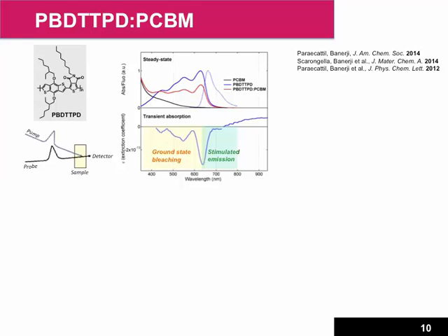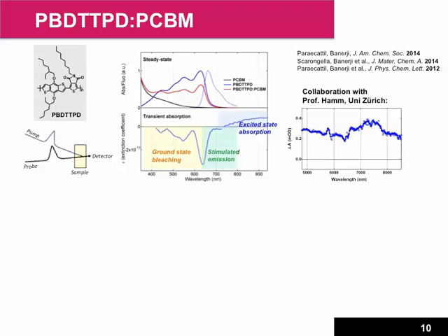And then this exciton will also absorb some light, and so you get a positive signature, which is called excited state absorption, where you can really then have the absorption spectrum of the exciton. And one thing we noticed, but I'll just show it, but we're not exactly clear about the reason, is that this excited state absorption actually extends extremely far into the infrared range. So it seems that the exciton really has a very broad excited state absorption, and this could be representative of some manifold of higher lying delocalized states. We're still working on this effect.